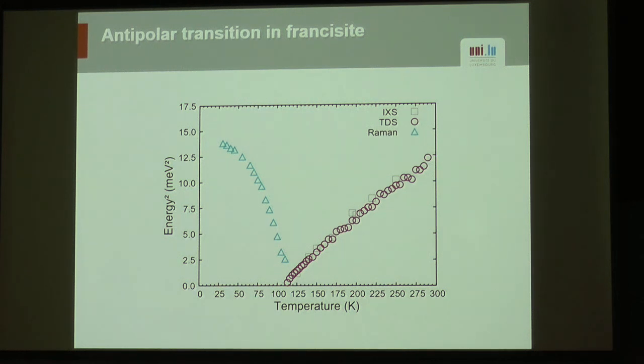Again, that really looks like nice soft mode behavior. You want this behavior to be linear close to the transition, which is the case, I would say, in a reasonably large temperature range. If you go a bit further down here or up, obviously, it starts deviating from linearity. Up there, I would argue that this can be due to some mode-phonon coupling that breaks down the soft phonon picture a bit. I'll come back to that. And here, I won't elaborate, but you might also start interacting with the magnetism that starts at about those temperatures. So those are expected, but the main message is that in all this range close to the transition, it really behaves like a very nice soft mode.